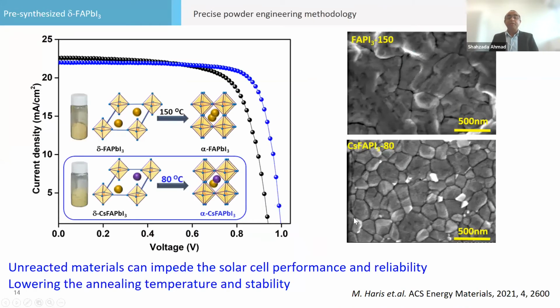And similarly, we have also been working on FAPbI3. We have been working on FAPI powder, and this is a self-processed powder, so you can just dissolve it in any ink, so it will be a semiconductor ink. And what we noted is that if you incorporate cesium, the annealing temperature goes drastically down from 150 to 80 degrees. Sorry, FAPI demands annealing at 150. So if it can be annealed at 80 degrees, it means we can also think about flexible surface deposition of the FAPI.